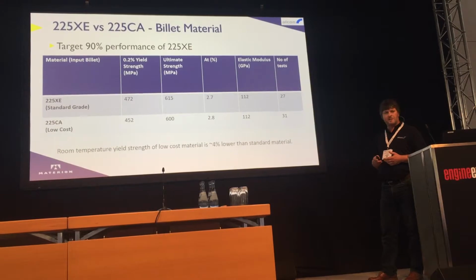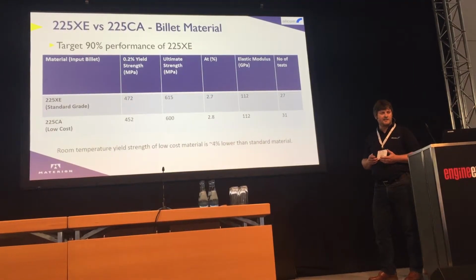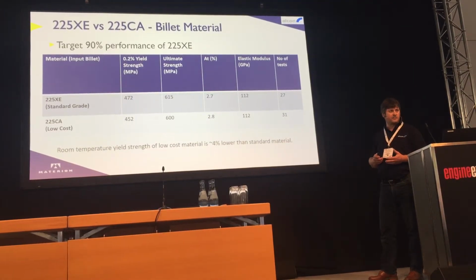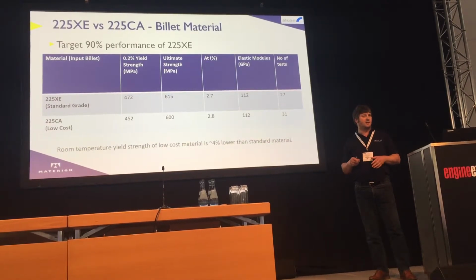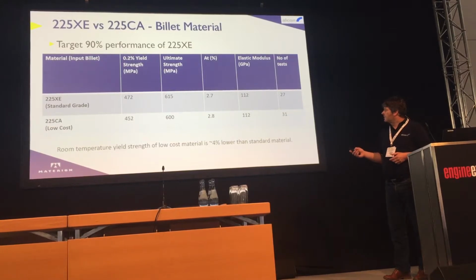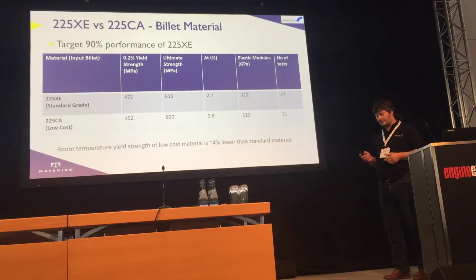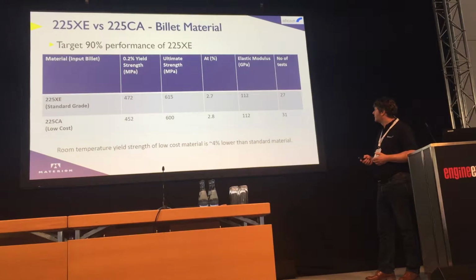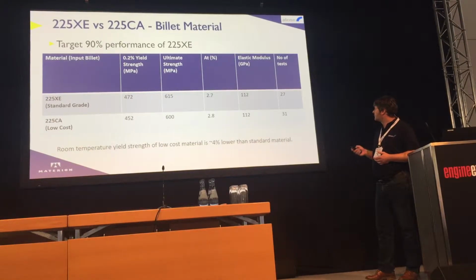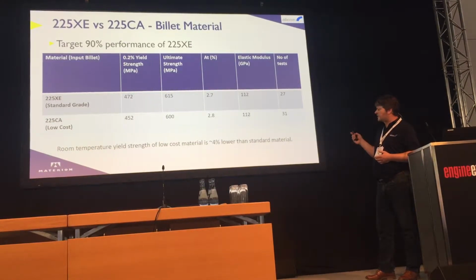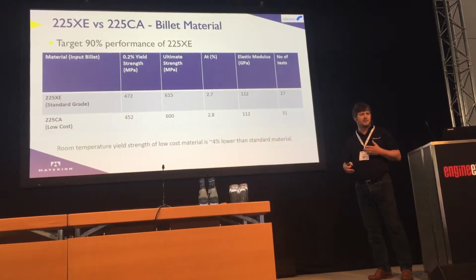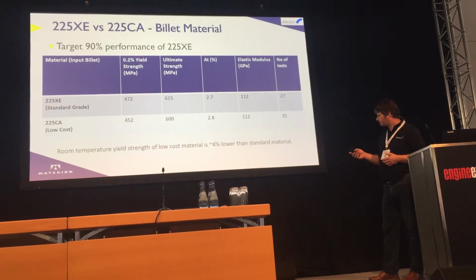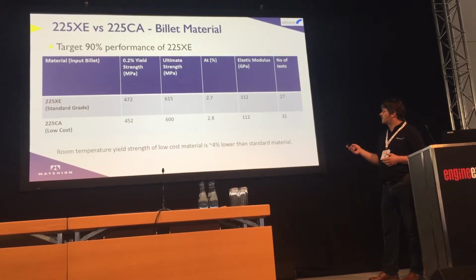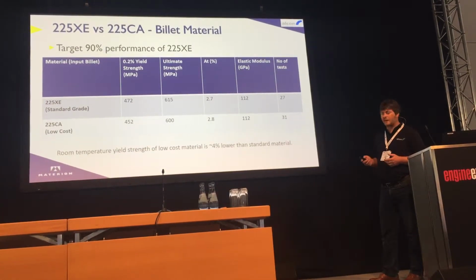So in terms of the 90% performance, we were comparing the alloy to a 225XE, which is an alloy that's been used for a long time, and we were looking at trying to achieve 90% of that performance at 50% of the cost. What we actually got to was very close to that, about 4% lower yield strength, very similar in terms of the elastic modulus, and the testing was carried out at Materion and also repeated at Jaguar Land Rover, so at 2 different sites. So in terms of our target achieving the 90% performance, we achieved that essentially.